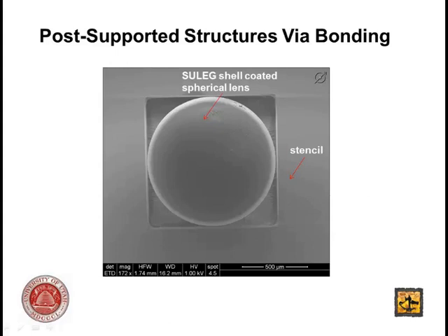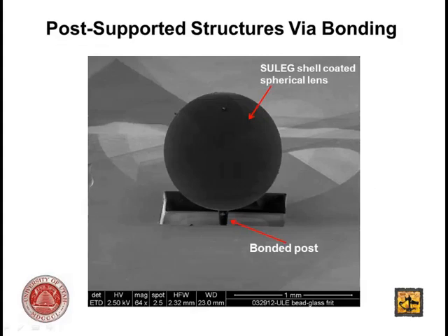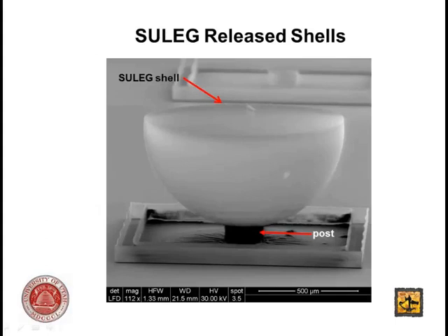From the top, this is how it looks. You have your stencil, then you drop that lens, and it just fits right in there. And after you remove the stencil, you end up with a structure that looks like this. So you have a bonded post and a sphere, so it looks a lot nicer. And after, of course, you go to the etching of the top and the sacrificial layer, you can remove the mold, and you end up with a shell.